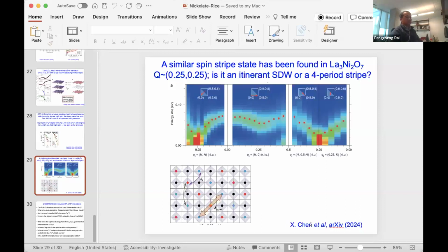So one of the issues is that this topotactic reduction is pretty drastic for the 112s. You're stripping out all the apical oxygens, and you go from nickel 3+ to nickel 1+. It's quite violent. And so there's been this debate whether this is really a true density wave or whether you simply have oxygen vacancies which order in this pattern. It reminds me of YBCO, right? The density wave signatures are very weak, like what you see in YBCO, whereas in the 438 material, the reduced trilayer, it looks very similar to LSCO, LBCO, right? You have a very pronounced stripe state. So you see the same kind of dichotomy that you've been seeing in cuprates.